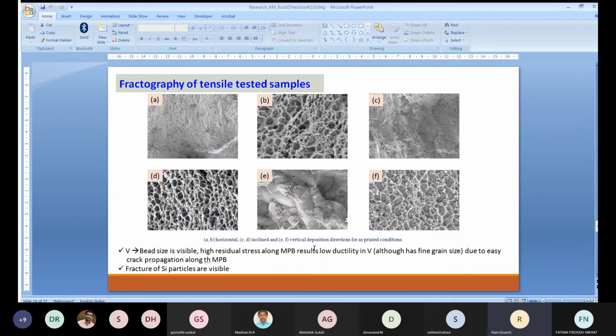And we did fractography studies to understand the fracture surface after the tensile testing. We mostly find dimples and fractured silicon particle regions, and we can see the melt pool shapes very clearly. Compared to the horizontal and inclined directions, in the vertical direction we can see the laser bead size very clearly. It is because you have high residual stress along the melt pool boundary, which results in lower ductility in the vertical direction, although you have a fine grain size. Because of the high residual stresses, crack propagation along the melt pool boundary is very easy. And as I said, the fracture of silicon particles was visible in all the cases.